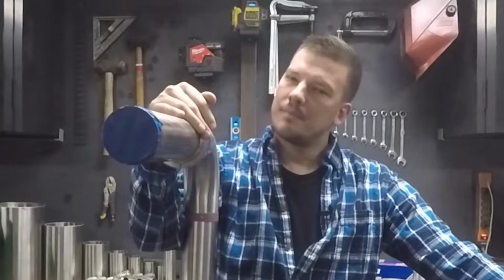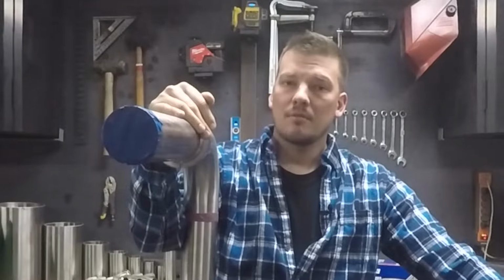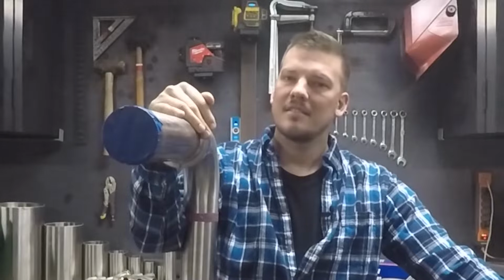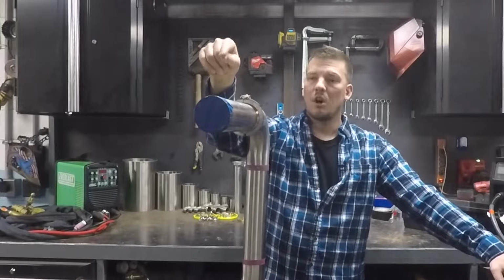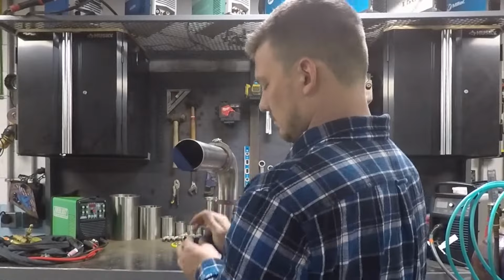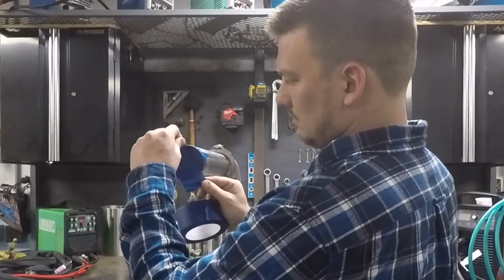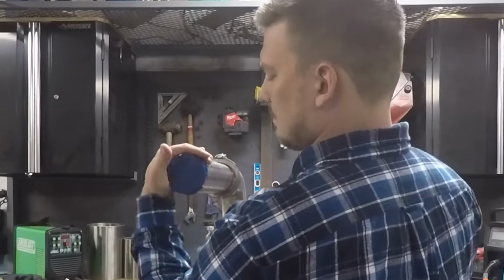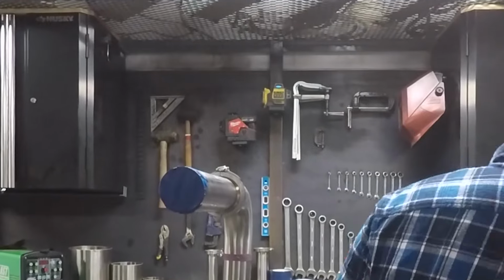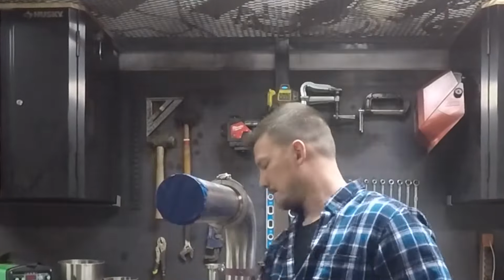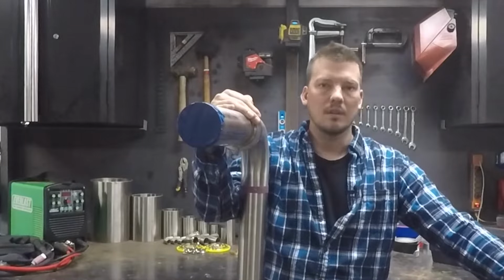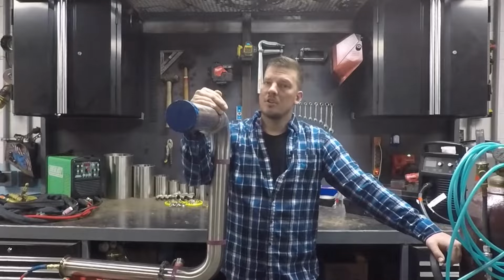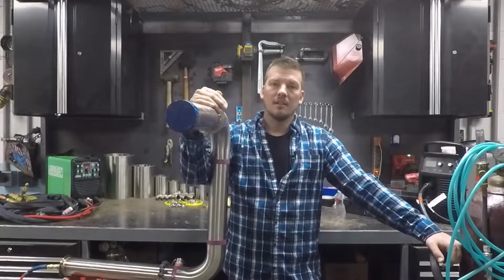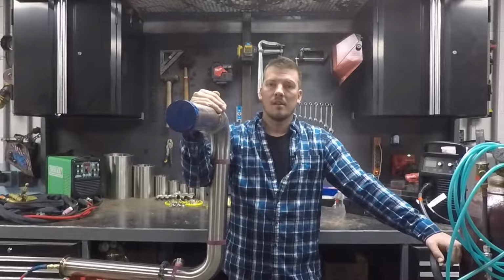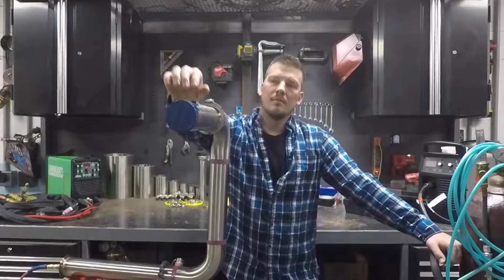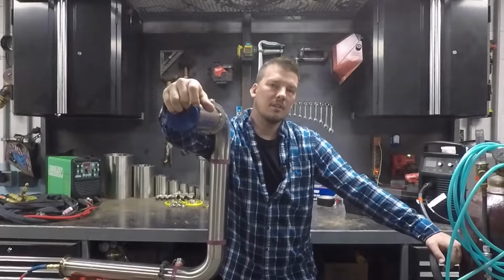A lot of people get caught up asking exactly what CFH I run on the flow meter, but remember that's not the only variable. Your exhaust opening also dictates your purge pressure. You can purge any given pipe at 5 or 25 CFH as long as your opening corresponds. The only difference will be in the time that it takes to push out all of that oxygen at 5 versus 25 CFH. On larger purges, you can blast the argon as high as you like until the oxygen is all gone.